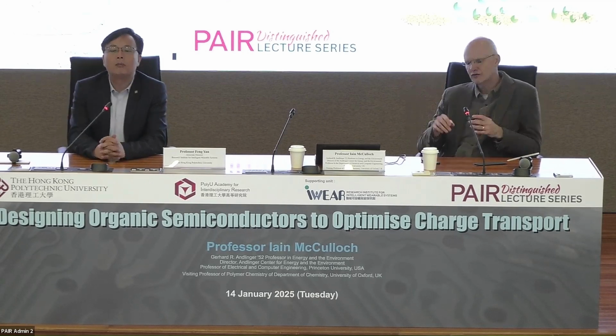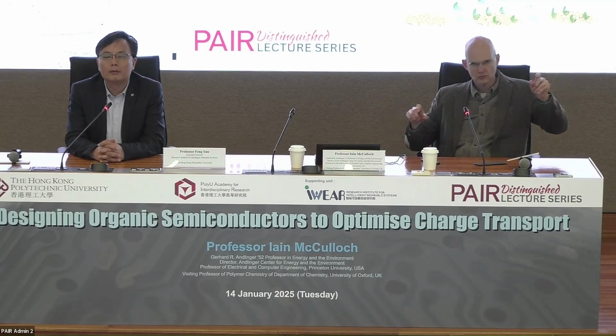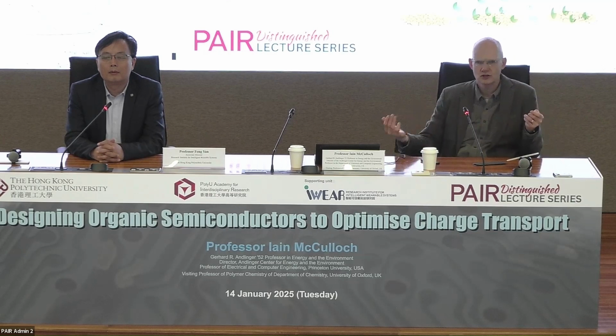There are different conflicting views on this, but some of the latest work is in the paper I showed, Jenny Nelson's Proceedings of the National Academy of Sciences paper. She shows that the mobility tends to have a monotonic relationship with length of chain, whereas in thiophene-like polymers, it's not like that. And the reason it's like that for these planar ribbon-like polymers is that the longer the chain, the larger the number of intermolecular contacts. The larger the number of intermolecular contacts, the faster transport you can achieve. So the length of it matters.